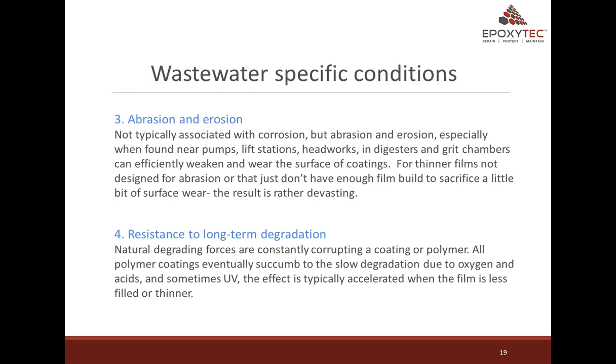Number four, resistance to long-term degradation. Natural degrading forces are constantly corrupting a coating or polymer. All polymer coatings eventually succumb to slow degradation due to oxygen and acids and sometimes UV. The effect is typically accelerated when the film is less filled or thinner.